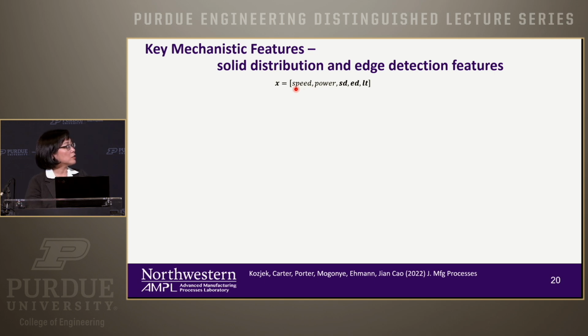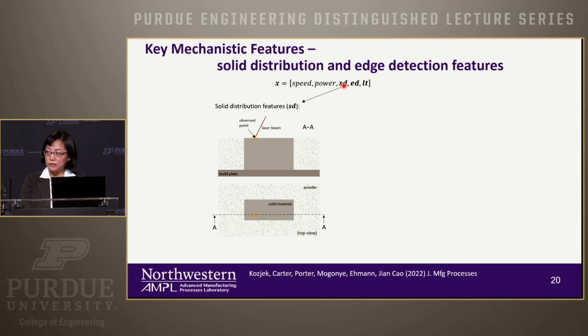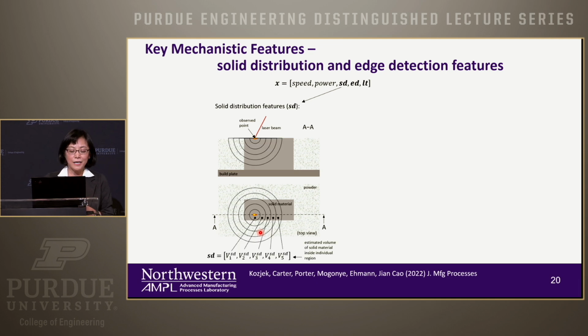So this gives us this idea about the features that we need for predicting the profile, right? So certainly you have the laser scanning speed, the power, and this SD is what I mentioned to you earlier. When you think about this, the temperature very much depends on material thermal conductivity and many other things. So if you have a solid part versus a powder part, you are going to see different behavior, right? So the way that we try to be agnostic to geometry is to develop this feature. You can think about this as a hemispherical region. If it's 100% solid, it's 1. If it's partially solid, you can calculate the percentage.